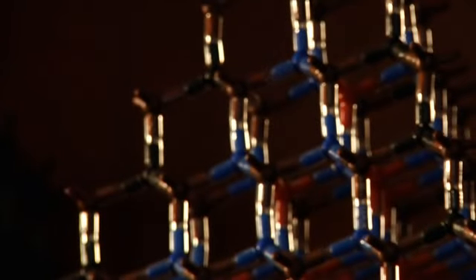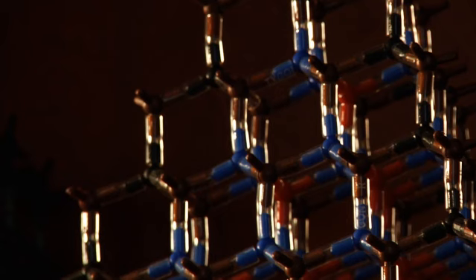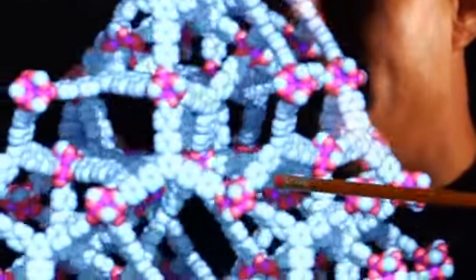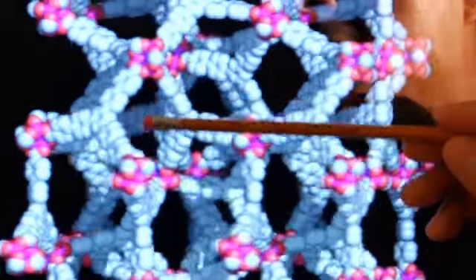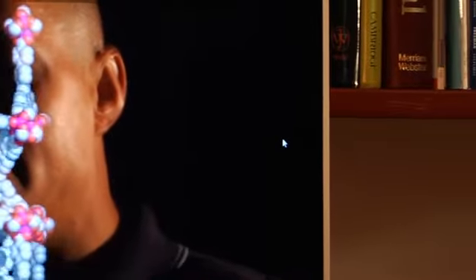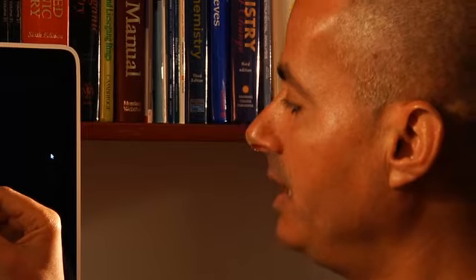And they're constructed from metal oxide joints and organic linkers. The linkers essentially hold these joints together into extended structures that have many pores that are vacuous, essentially. The nice thing about these structures is that, as you can see, they're highly open structures. And suspended within this openness are the parking spots. These are the little red and white spots you see here that are stitched together to make the framework of the material onto which carbon dioxide can be bound and held into place.